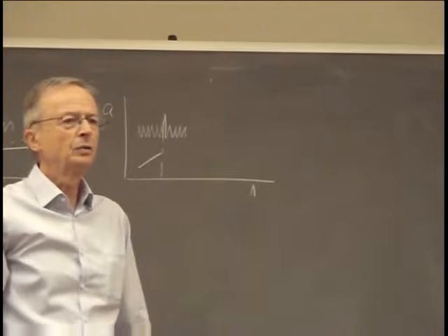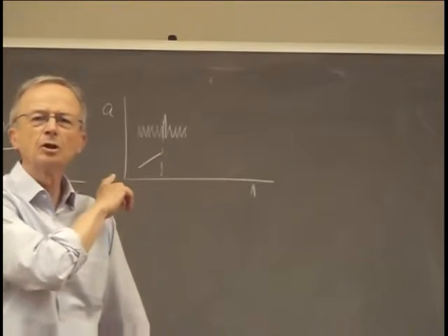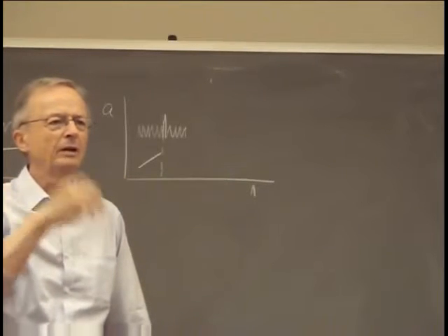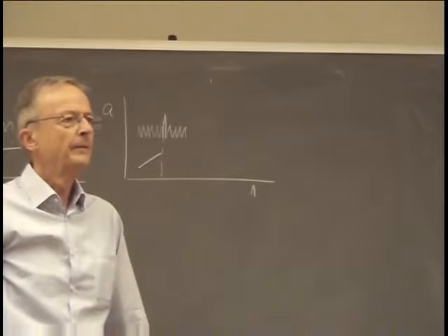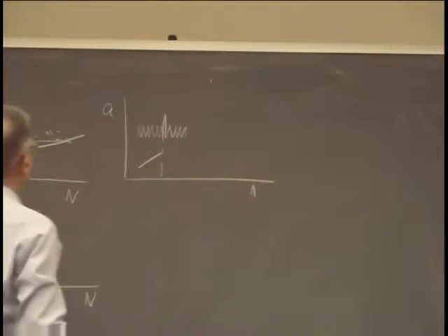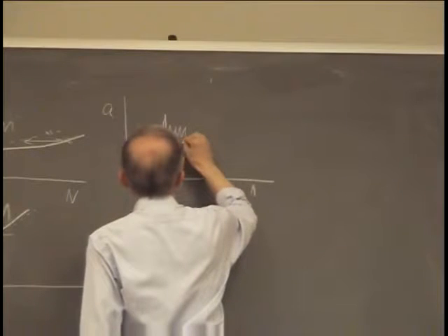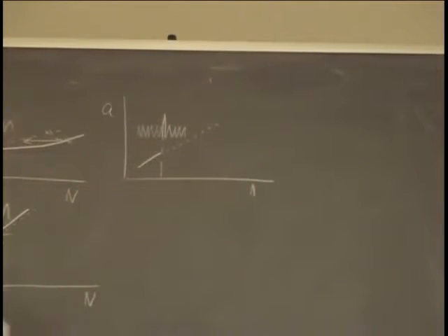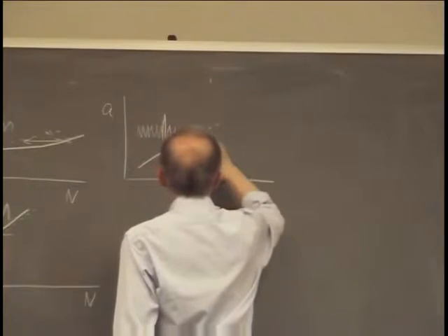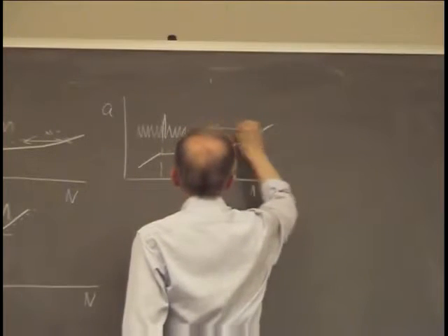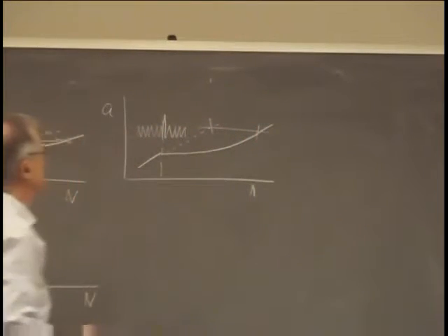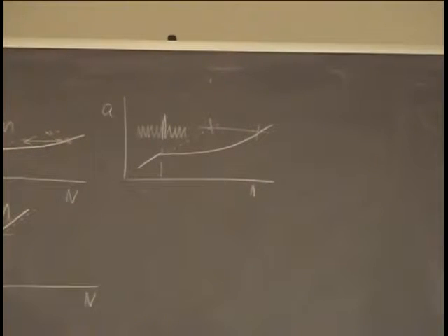So the increase in crack size due to the single overload can't be shown in the diagram because it's too minute, maybe it's a fraction of a micron. But it has another effect, so this is the expected course of our crack. What happens is this here, a delay, a substantial delay, caused by the single peak overload, which sounds a bit perverse. You apply an overload and you gain life.